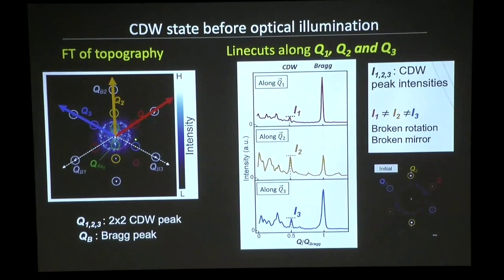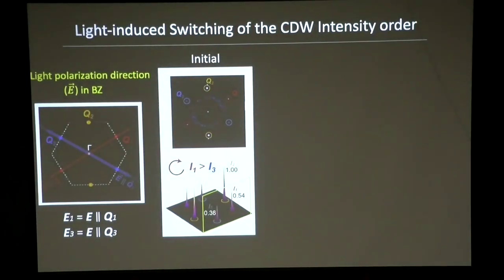Now, like it was seen before, if you take line cuts along the three directions, you have the Bragg peaks. They have different heights, but also the charge density wave peaks, 1, 2, 3, they also have different heights. This is not surprising. This has been seen before. These three intensities being different tells you that two kinds of symmetries are broken. First, rotational symmetry is broken, but also because this peak and this peak don't have the same intensity, mirror symmetry is also broken. Okay, so now I'm going to show you data on what happens when we turn on light.